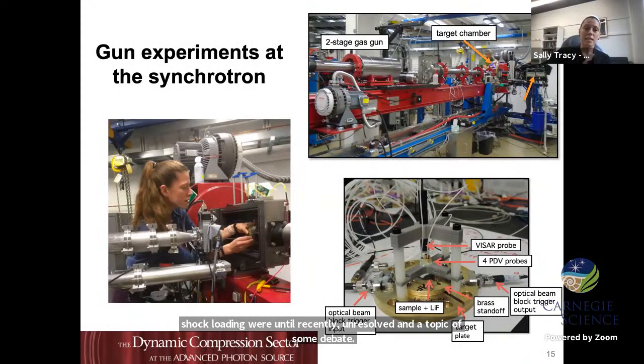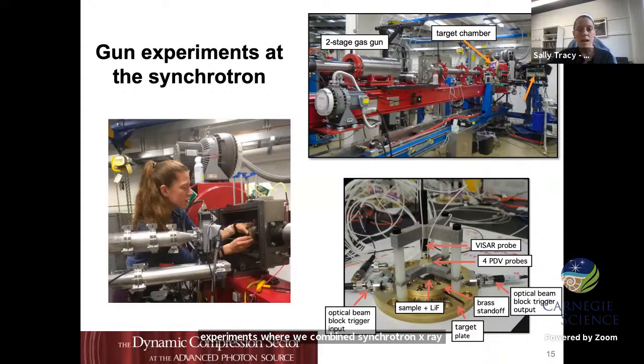So in order to address this, we carried out a series of experiments where we combined synchrotron X-ray diffraction with gun-based loading at a facility known as the dynamic compression source, which is part of the Advanced Photon Source in Chicago. And this slide just shows a few photos of the experimental setup, including the length of the 2-stage gas gun shown here. The bottom image on the left shows me mounting a target in the target chamber. And the bottom right figure shows an example of what the types of targets for these experiments look like, where a SiO2 sample is mounted on top of this brass plate under all these experimental probes.